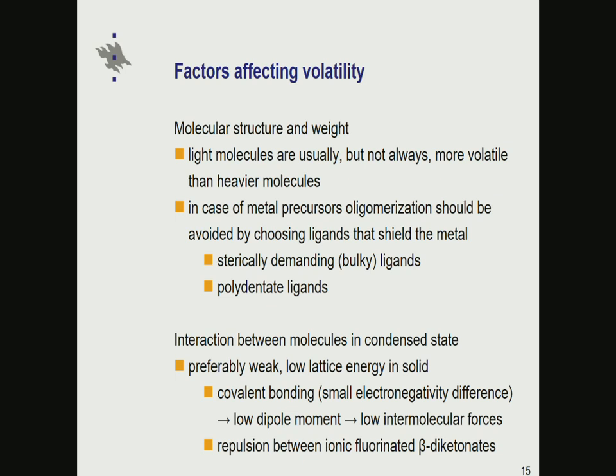But then the factors affecting the volatility. It's not very straightforward to reason how volatile a given compound would be. But there is a rule of thumb in general. Light molecules are generally more volatile than heavier molecules. That means, in the case of metal precursors, that one should avoid the fact that metal precursors quite often form dimers, trimers, or even higher oligomers. So one should try to control that by choosing ligands that shield the metal against oligomerization, meaning sterically demanding or bulky ligands, and polydentate ligands. I will show you examples of this as we proceed.